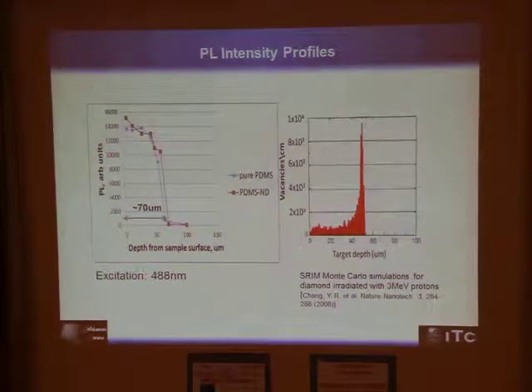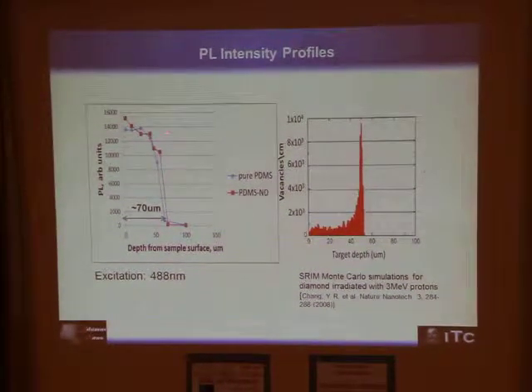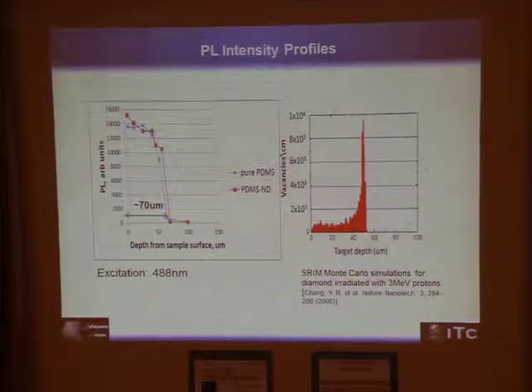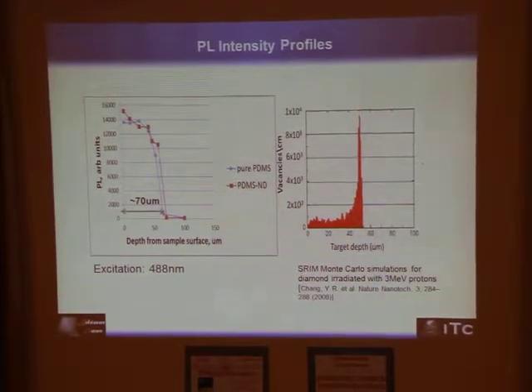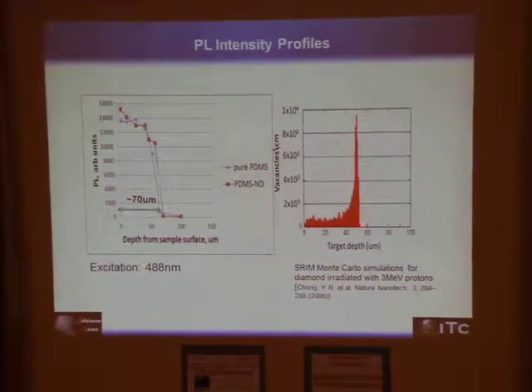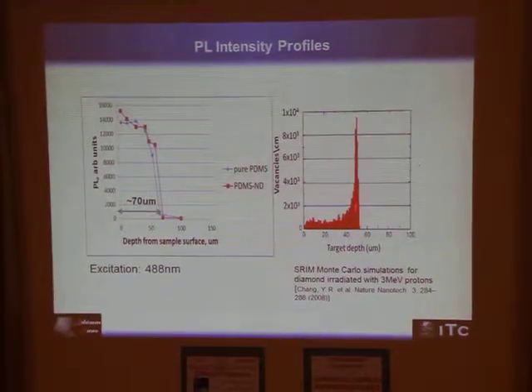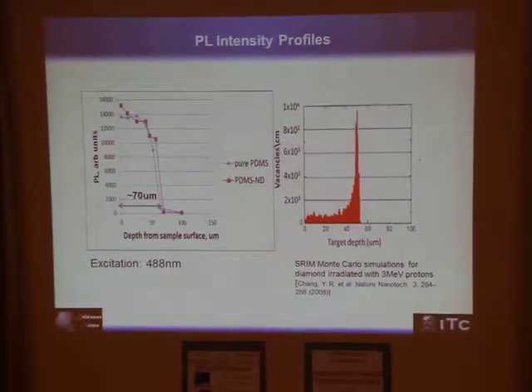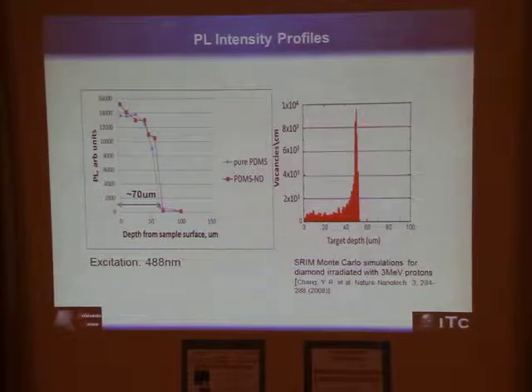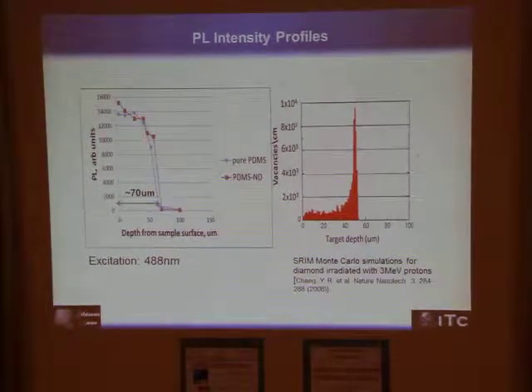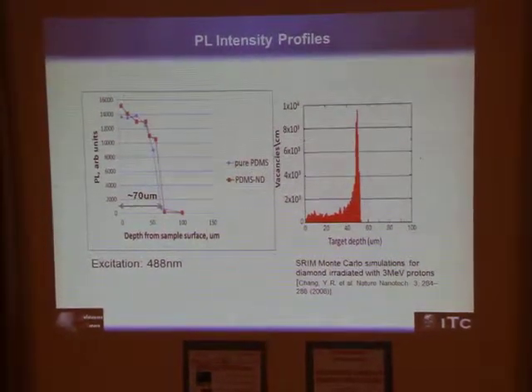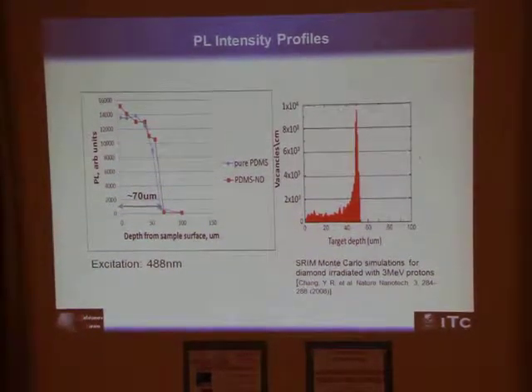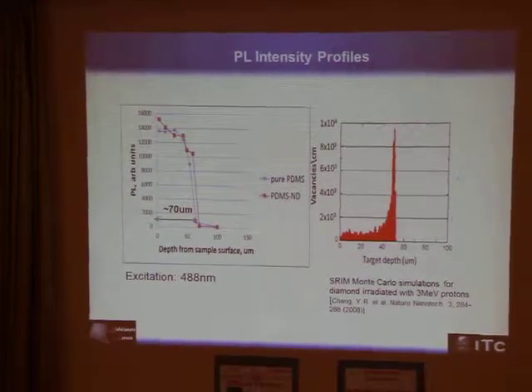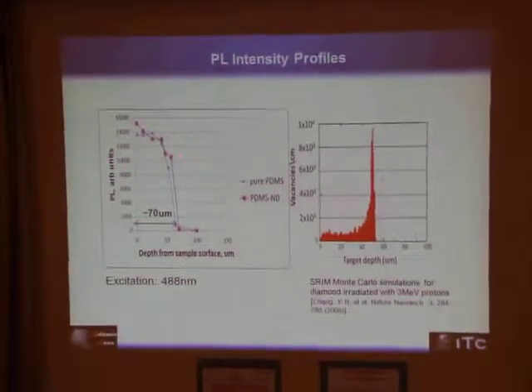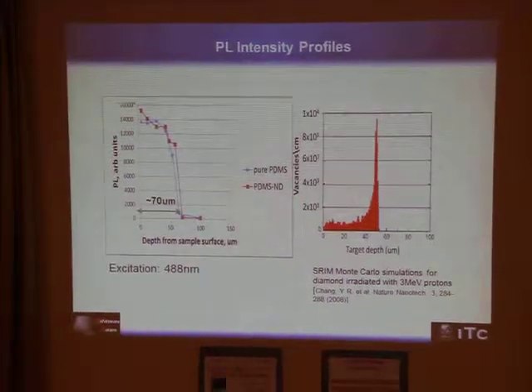So in general, we were interested to see if there are any interesting events at the depths corresponding to the place where the proton stops and where high vacancy formation is typically expected. However, we didn't see anything outstanding in this region. This tells us that the source of photoluminescence is not a damage event at this high vacancy production region.